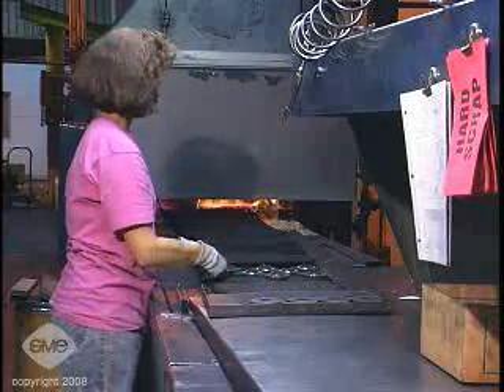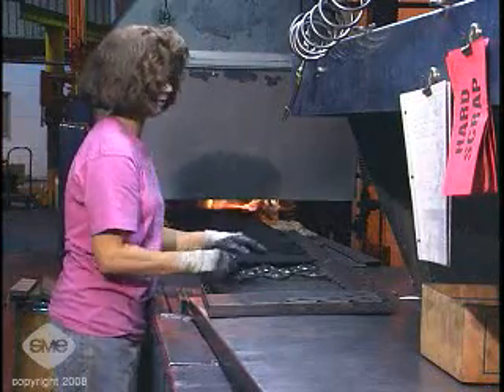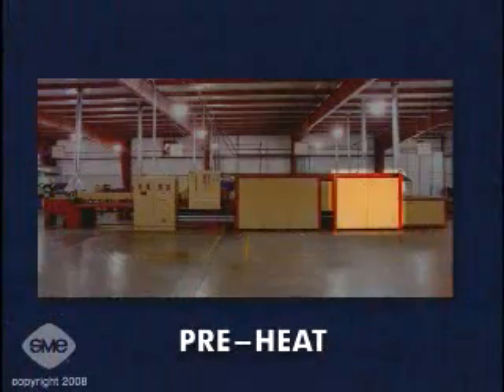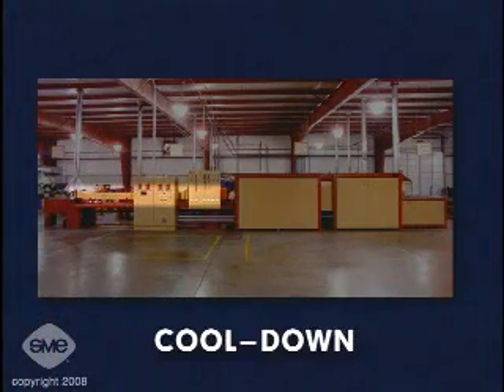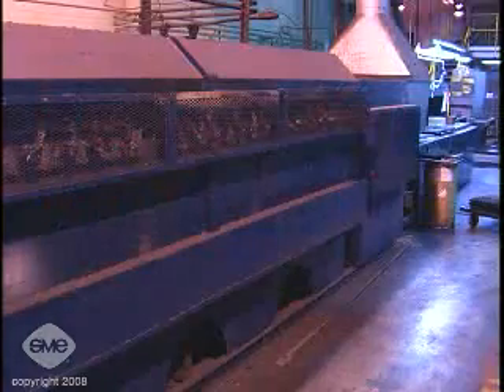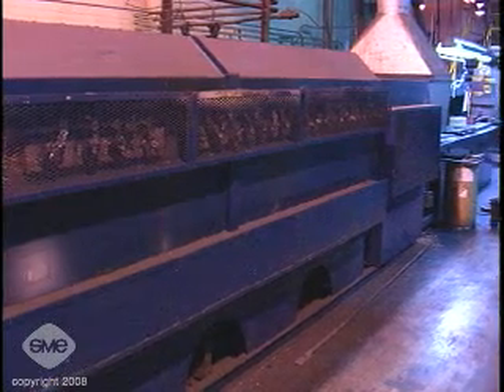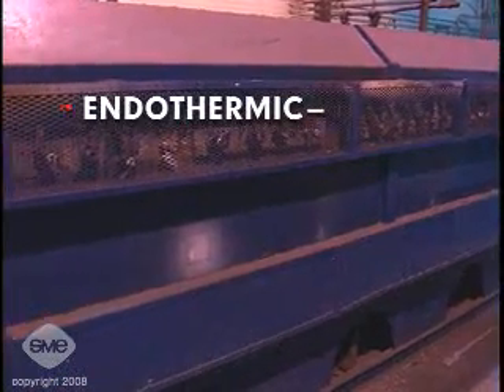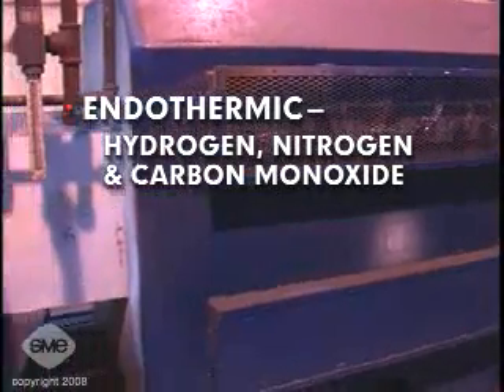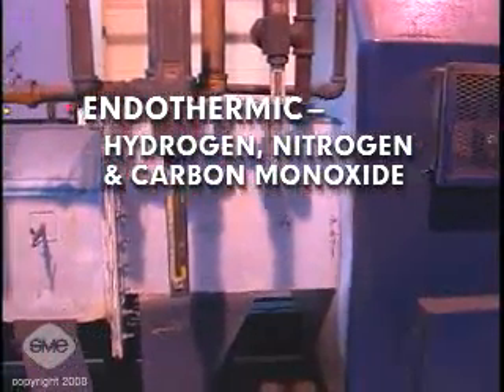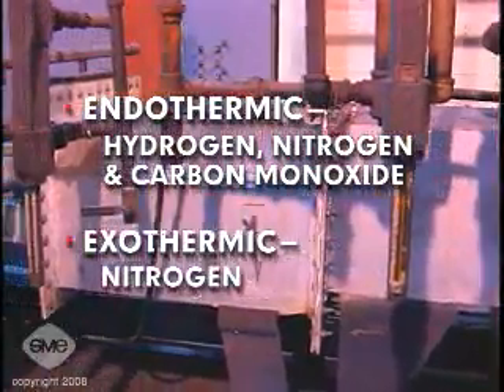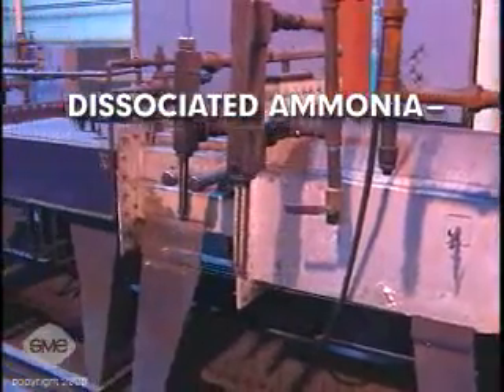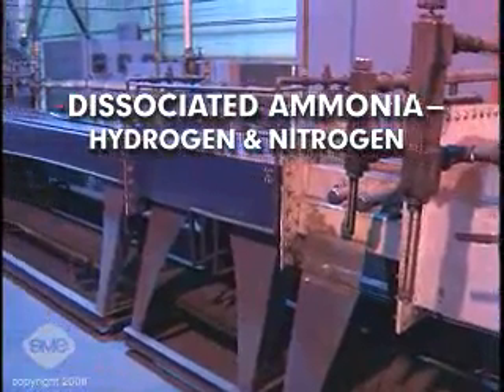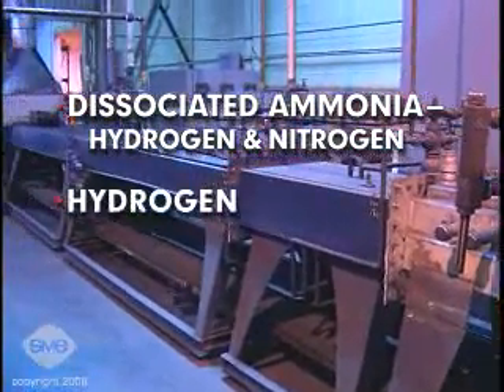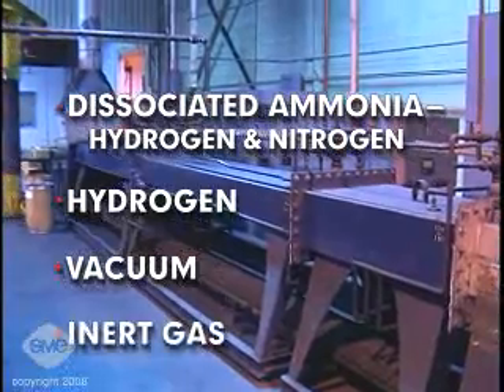After pressing, parts are transferred to the sintering furnace. Sintering furnaces include preheat, high heat sintering, and cool-down zones, each having a controlled atmosphere. Depending on the base metal of the part, the atmosphere of the sintering furnace may be endothermic, which is composed mainly of hydrogen, nitrogen, and carbon monoxide; exothermic, which is composed of nitrogen mainly; dissociated ammonia, which is hydrogen and nitrogen; or entirely hydrogen, vacuum, or inert gas.